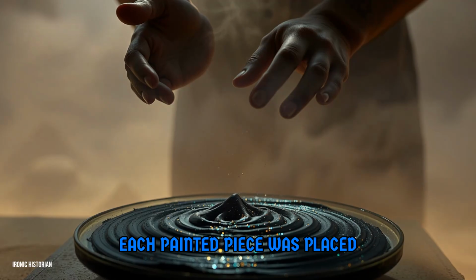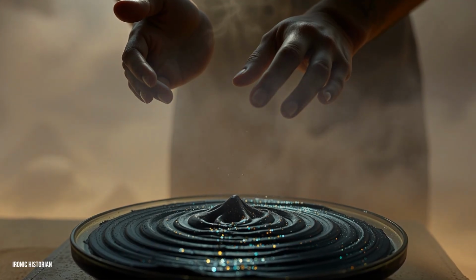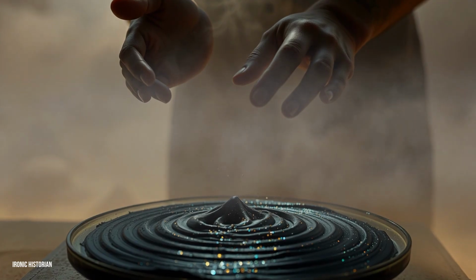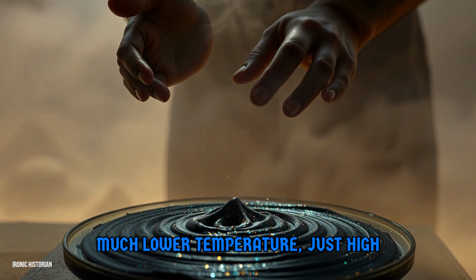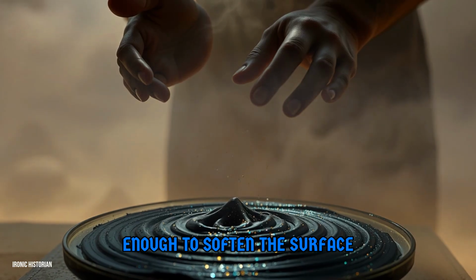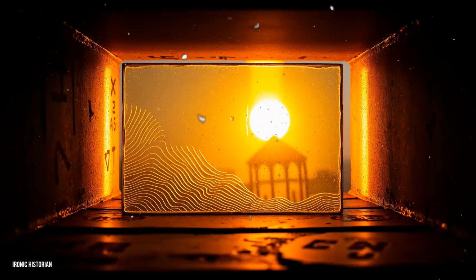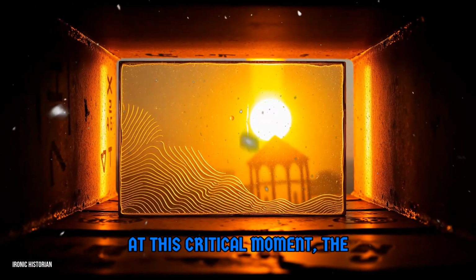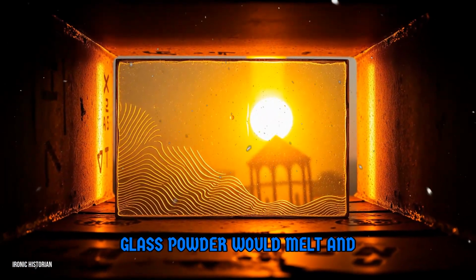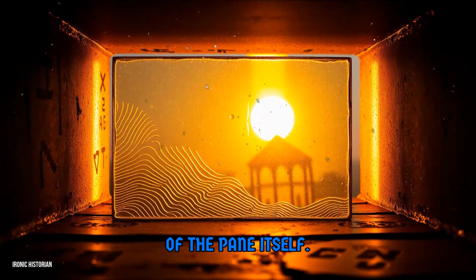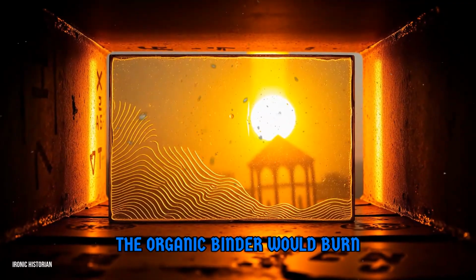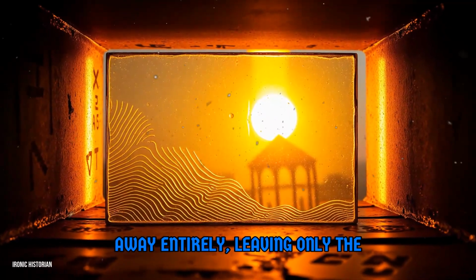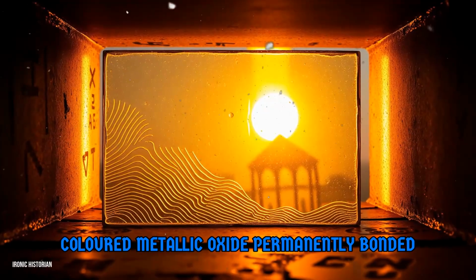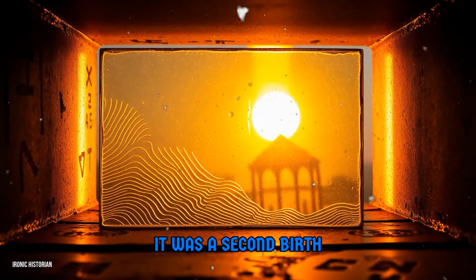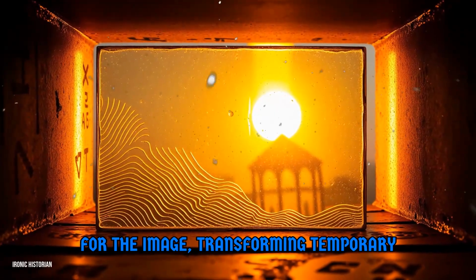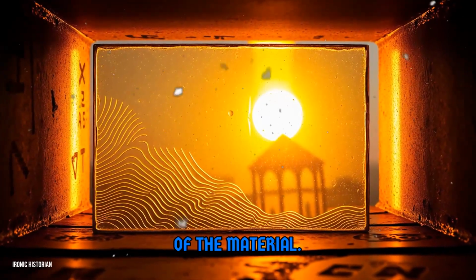Each painted piece was placed in a small, specialized kiln, separate from the roaring glass furnaces. It was fired at a much lower temperature, just high enough to soften the surface of the window glass ever so slightly. At this critical moment, the particles of the painted-on glass powder would melt and fuse inseparably with the surface of the pane itself. The organic binder would burn away entirely, leaving only the colored metallic oxide permanently bonded into the glass. It was a second birth for the image, transforming temporary paint into a permanent part of the material.